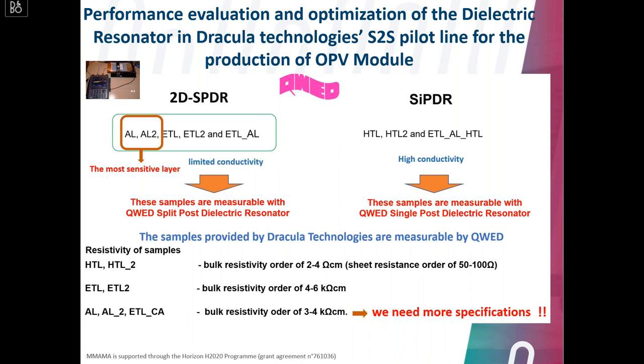And the second way is the SiPDR measurement, which in general is more suitable with highly conductive materials like the HTL or the top electrodes. So the good news for us is that in both cases, with the two methods, our printed layers are measurable with this technique, which allows us to determine in all cases the resistivity of the different printed layers.